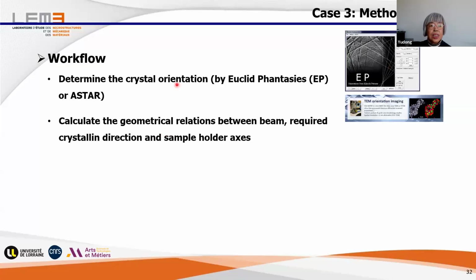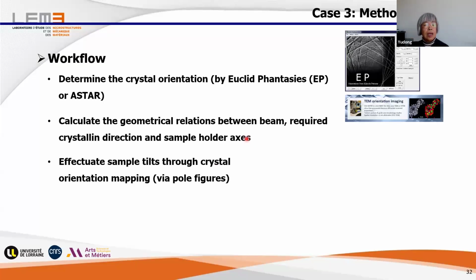Okay, and then with this orientation, the software will calculate the geometrical relation between the beam, the required crystalline direction, that means the reflection plane normal, and the tilt axis of the sample holder. And then the software will tell you how many degrees and in which direction you should tilt your sample to reach the position of either the two-beam condition or the zone axis condition.